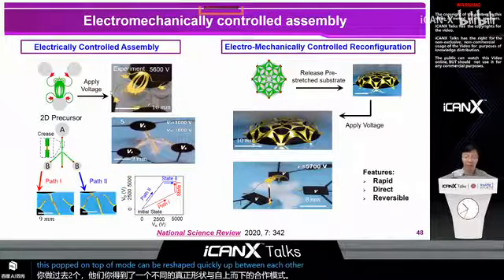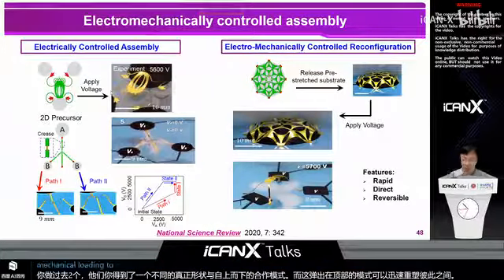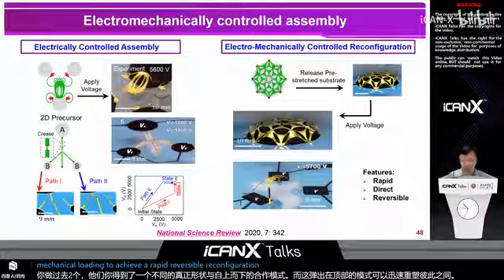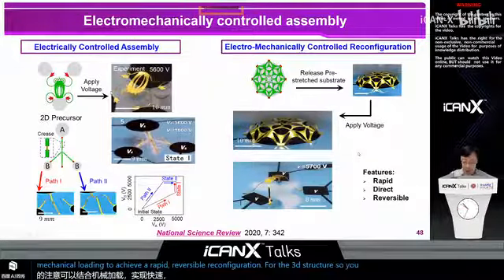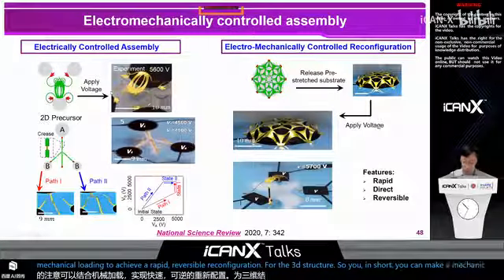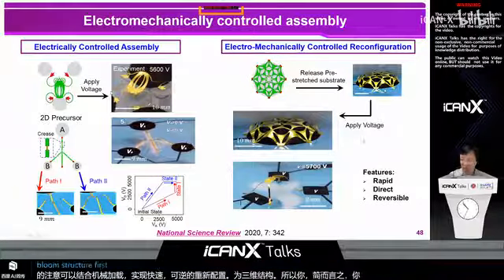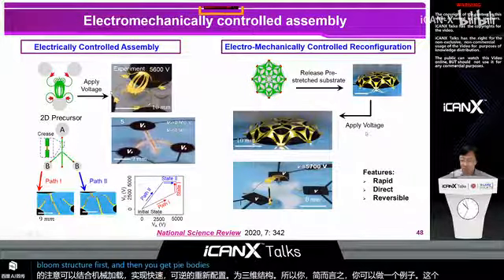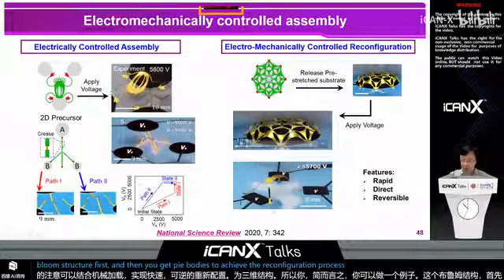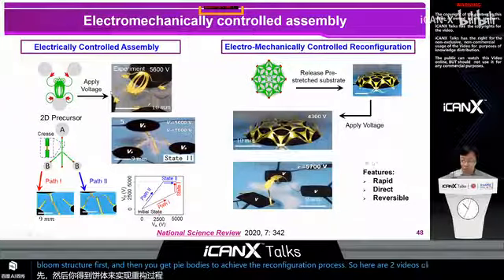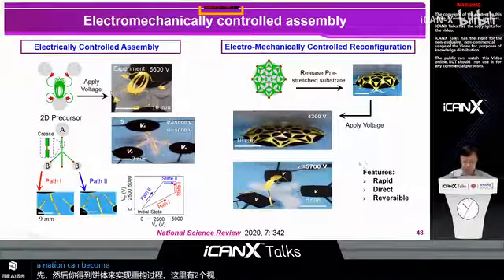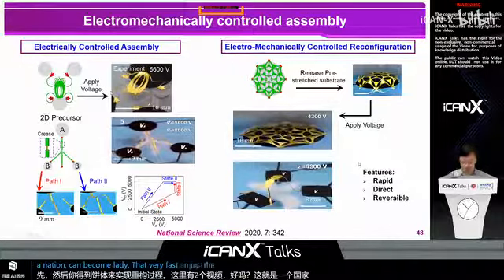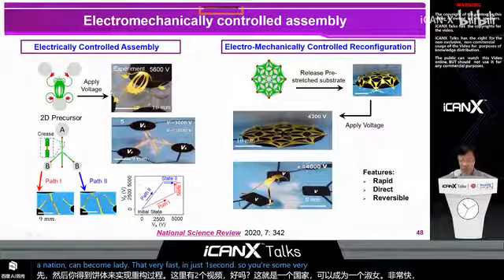And this electrical loading can be combined with the mechanical loading to achieve a rapid reversible reconfiguration for the 3D structure. So in short, you can mechanically assemble this dome structure first, and then you can apply voltage to achieve the reconfiguration process. So here are two videos. And this reconfiguration can be completed very fast, in just 1 second. So it's a very fast reconfiguration process.